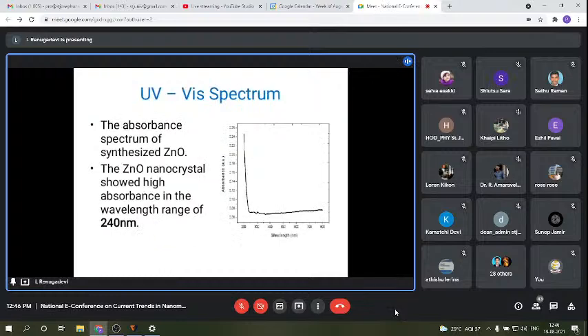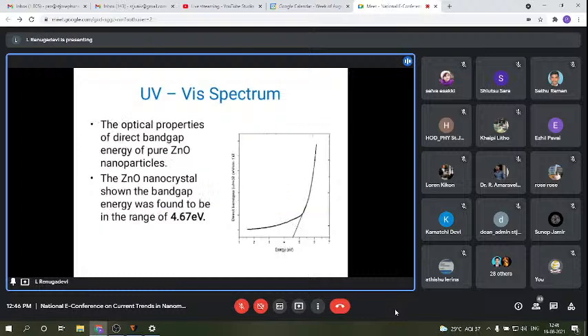This is the UV visible spectrum, the graph of absorbance and wavelength. In the absorbance spectra of the pure zinc oxide, it shows the high absorbance in the wavelength range of 240 nanometer. This is the graph for direct band gap energy of the pure ZnO nanoparticle. The band gap energy was found in the range of 4.67 electron volt.